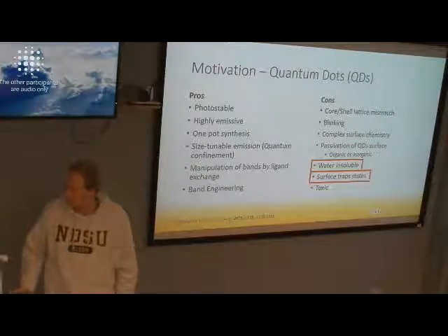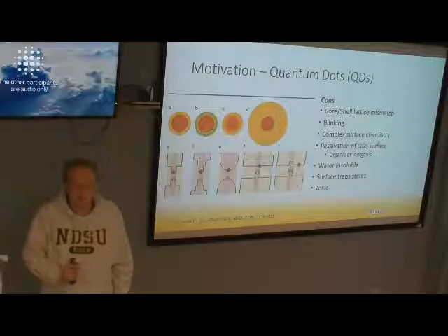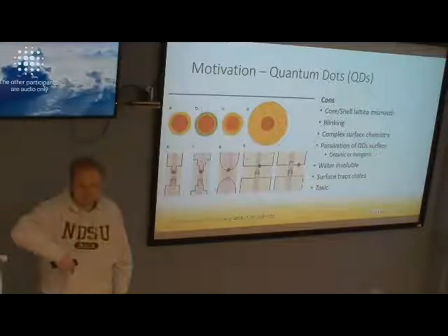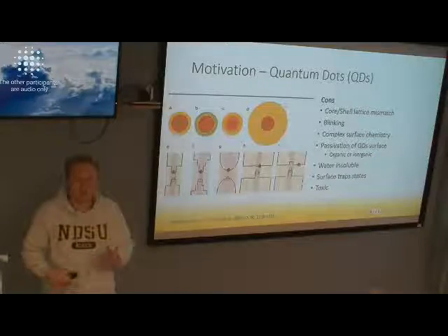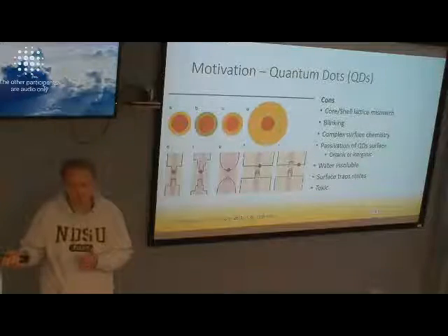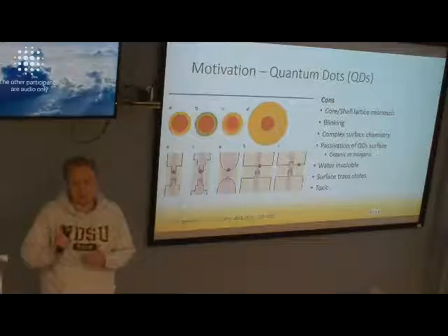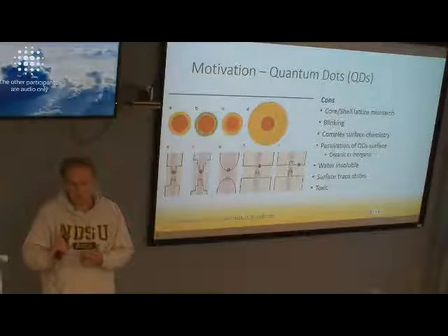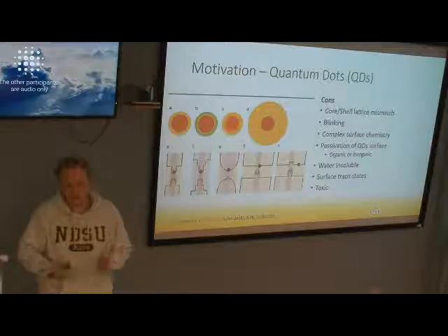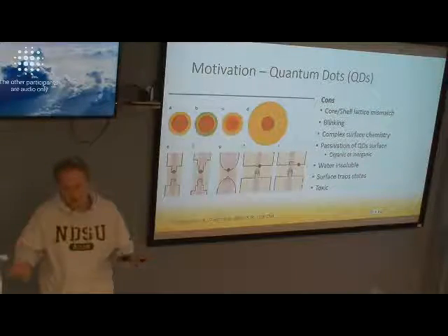But wait, why does NMR not work, or what was that all about? So NMR, do you understand how NMR works? Okay, so you have your nucleus spin that flips, and if you're in an environment that allows that to flip back rapidly, the signal won't be processed by the NMR machine. Quantum dots facilitate the spin flip back, the nucleus goes back to normal, so you don't get the frequencies in the NMR. Somewhat, yeah. So then it rapidly decays, and then it's either totally gone or very, very broad.